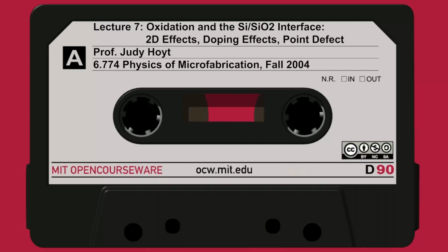So here's an example of LOCOS. Remember, you start with a silicon substrate. You put down a thin oxide, which is a pad oxide, which reduces the stress on the silicon due to the silicon nitride, and you put down silicon nitride and pattern it. Silicon nitride is a reasonably good mask, as oxygen cannot diffuse through it, so the oxidant diffuses in here and only oxidizes on the left side. So this is what the LOCOS structure looks like, just keep it in your mind as the starting structure before you do oxidation. That's what it looks like.